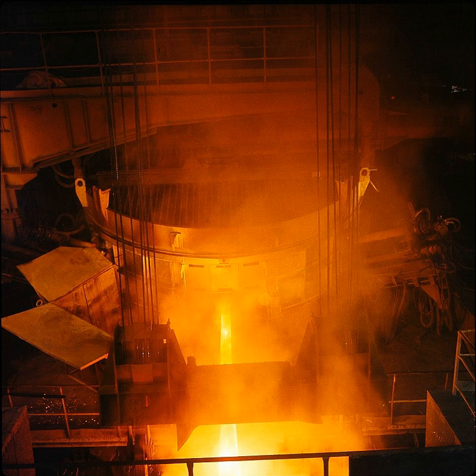More slag formers are introduced and more oxygen is blown into the bath, burning out impurities such as silicon, sulfur, phosphorus, aluminium, manganese, and calcium, and removing their oxides to the slag. Removal of carbon takes place after these elements have burnt out first, as they have a greater affinity for oxygen. Metals that have a poorer affinity for oxygen than iron, such as nickel and copper, cannot be removed through oxidation and must be controlled through scrap chemistry alone, such as introducing the direct reduced iron and pig iron mentioned earlier.